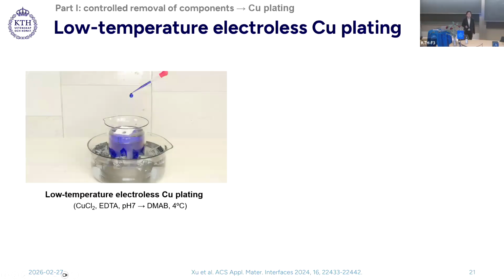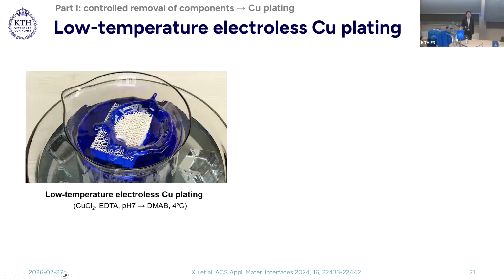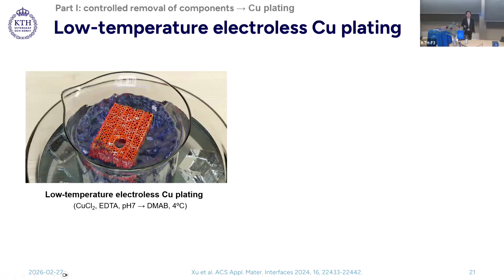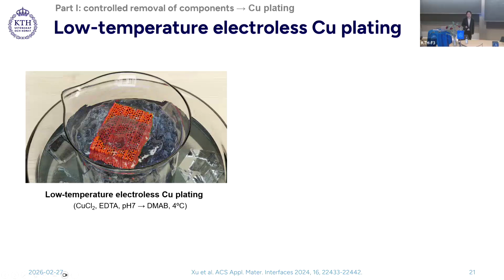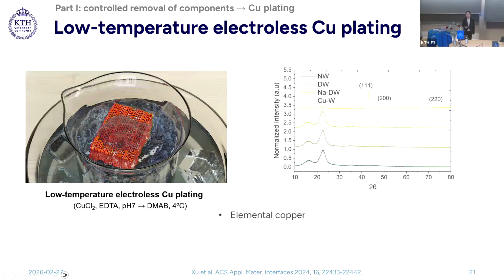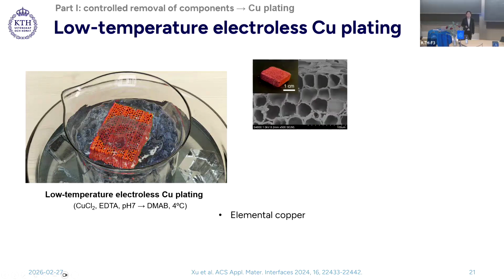The engineered wood template was then used to prepare a hierarchical porous composite. Here, a low-temperature electroless copper plating was selected to decrease the rate of metal ion reduction, thereby preventing the blockage of porous structure. XRD analysis confirms the synthesis of elemental copper. The obtained composite has a reddish-brown metal-like color.